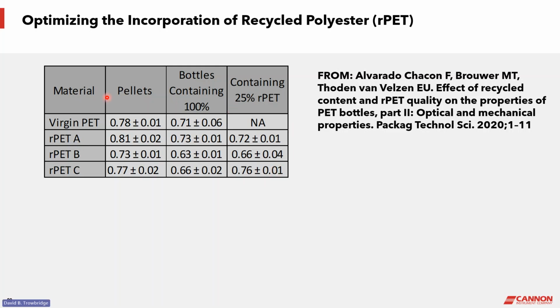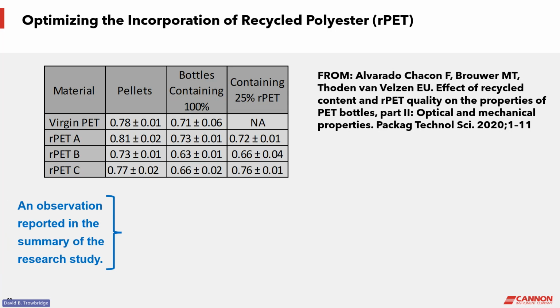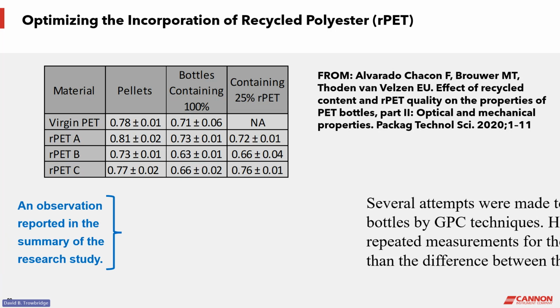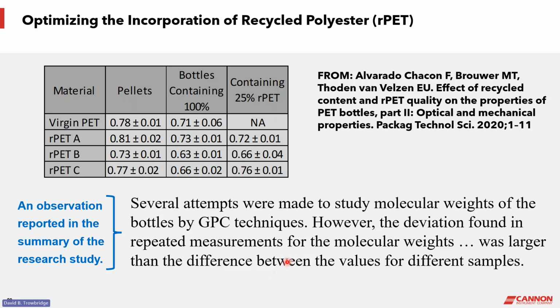So the point here is that this very careful analysis done with a lot of scrutiny was done with intrinsic viscosity. In fact, they stated that they initially attempted this with GPC. They studied molecular weight of the bottles by GPC techniques, but they reported that the deviation found in the repeated measurements for the molecular weights was larger than the difference between the values for the different samples. So what it meant was they had to give up on the GPC approach and redo the study using intrinsic viscosity because it could differentiate at this level.